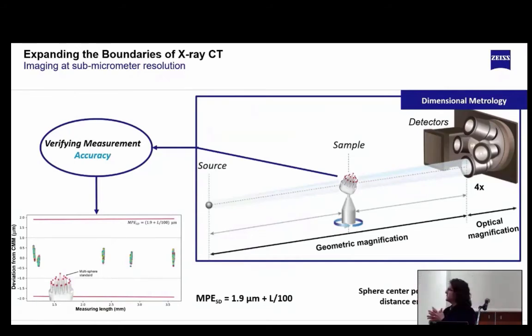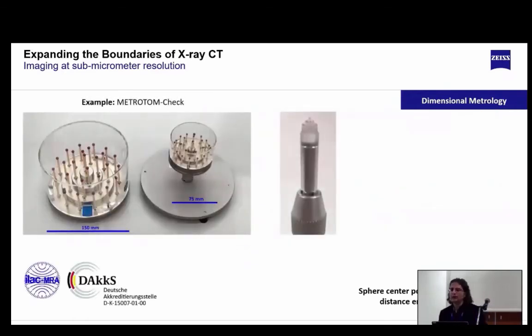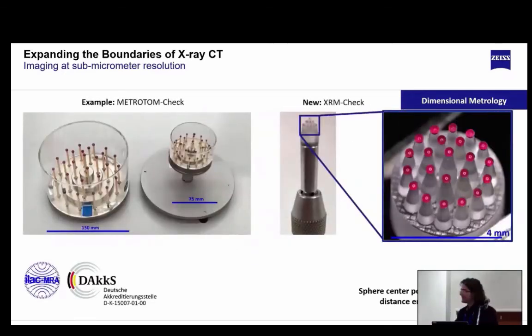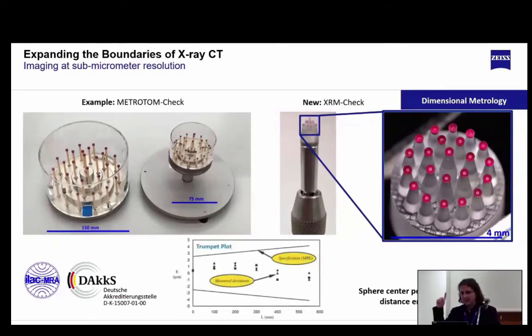And you can see that deviations are below 1 micron. But to give a little bit of room, since this has to work for several systems that we send to the field at different locations, we provide a maximum permissible error of 1.9 plus L over 100, which if you are familiar with metrology, is the typical way to provide that in CMM. And we did this because we have experience already with the traditional metrotomes that we provide on site. We have been doing this, I think, for more than 8 years already, probably more than 10 years,